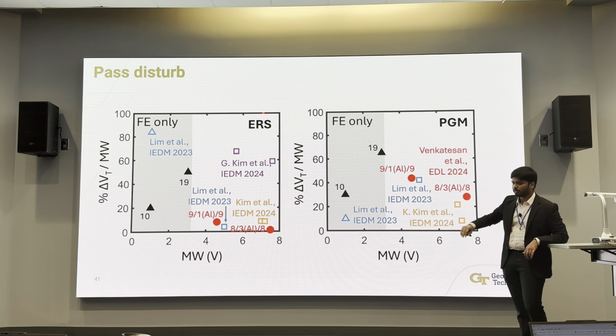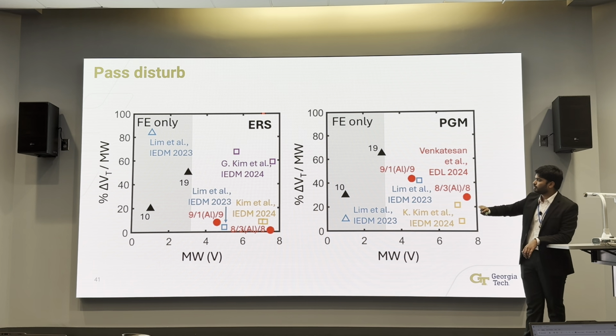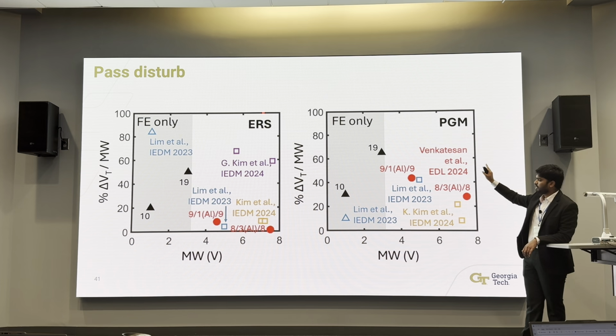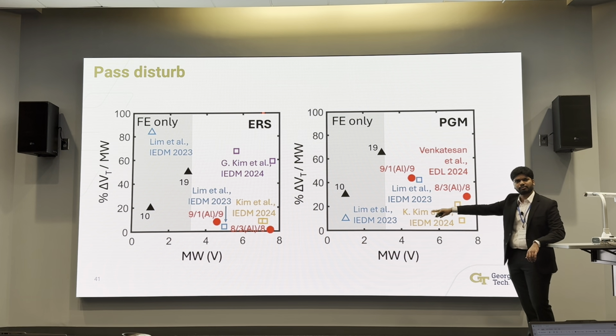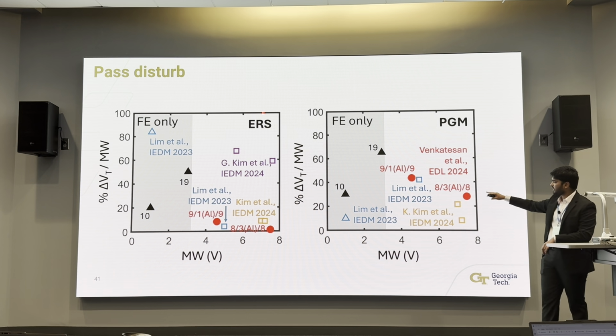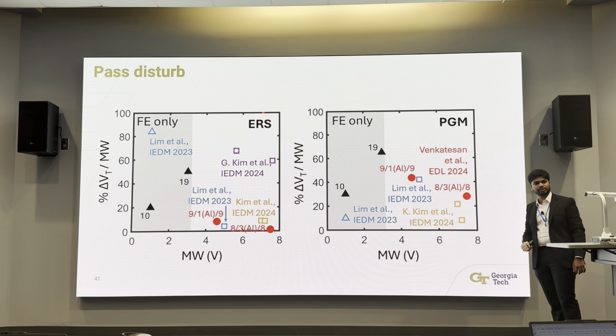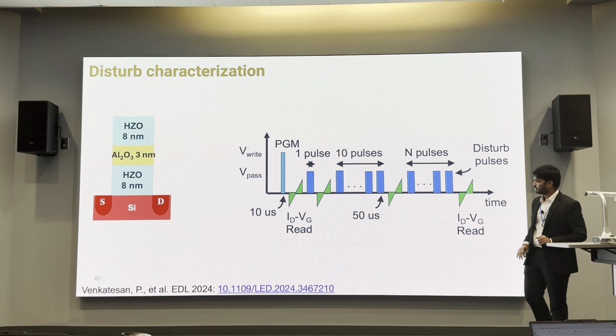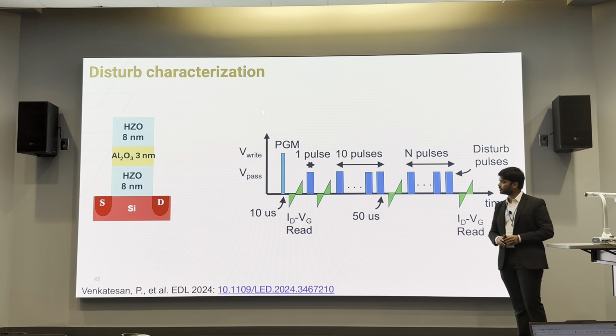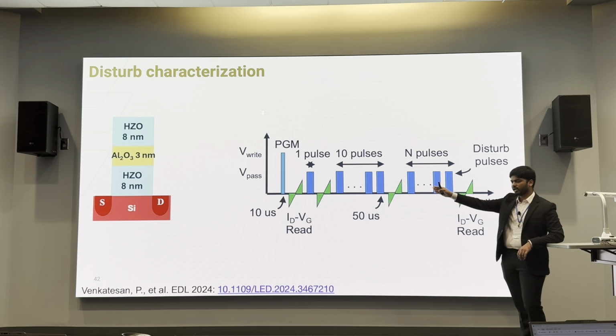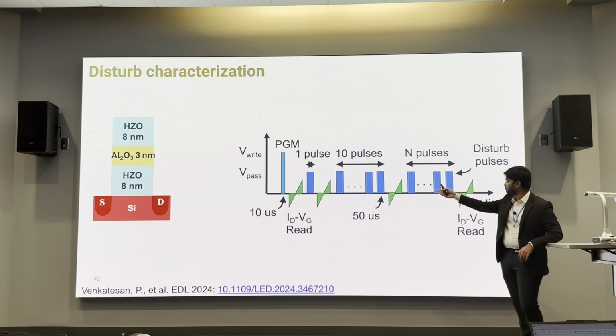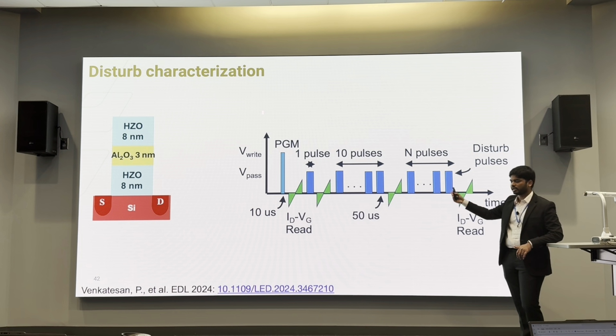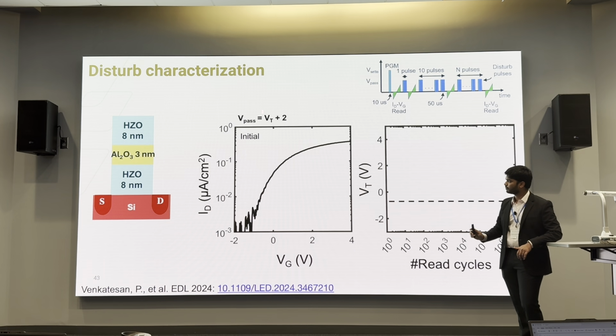So here we see a benchmark, and when we apply this threshold voltage, this is for the erase and program states, we see that we do not have much of a problem with the erase state, but with the program state, we see 20 to 60% degradation in the threshold voltage when we apply the pass voltages. So how is disturb characterized? So we program the device, we measure the IDVG characteristics periodically, and we apply a positive pass voltage of VT plus 2 n number of times and characterize the IDVG characteristics.